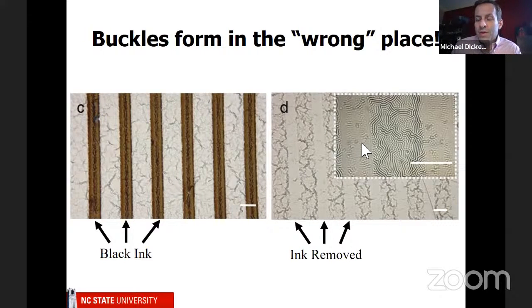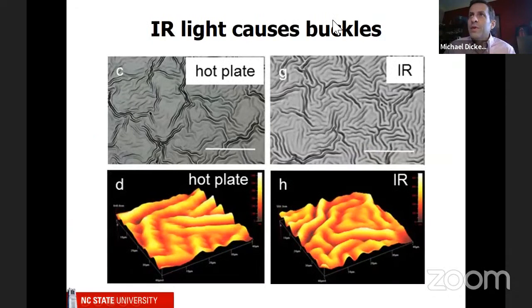So we then did a very simple experiment. We said, okay, let's take our film and heat it on a hot plate. If we heat it above the glass transition temperature of the polymer, which is about 100 degrees, we get wrinkles. If we take the same film and apply IR light, it actually gets hot enough to form wrinkles. So what that means is you don't even need the black ink. And so then the question is, well, why is it not forming where the black ink is located?